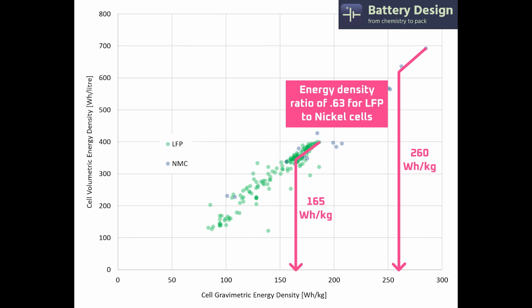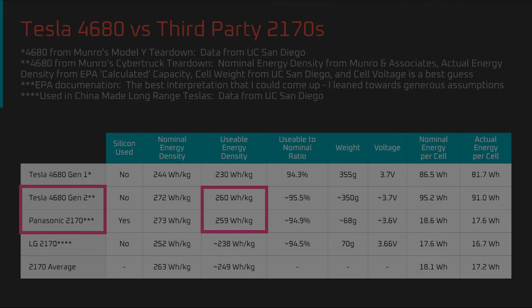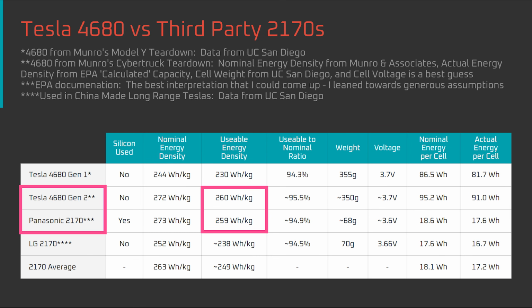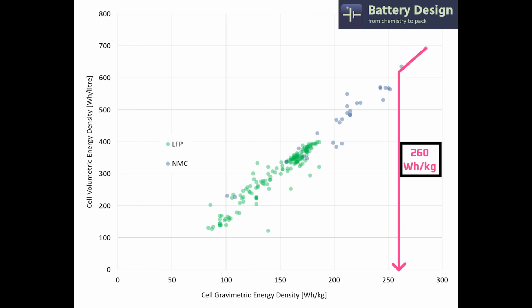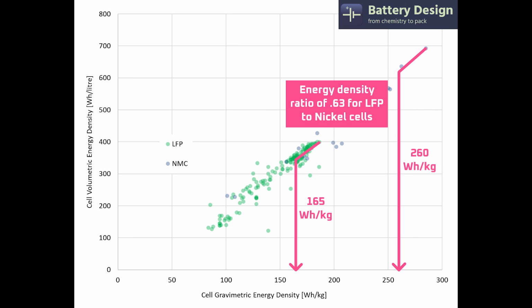Now that we've controlled for form factor using prismatic cells, let's apply that ratio to cylindrical cells. Cylindrical cells, such as the Generation 2 4680 and Panasonic 2170, have a usable energy density of 259 and 260 watt-hours per kilogram, which roughly aligns with the 260 watt-hour per kilogram usable energy density figure I estimated for a prismatic nickel-based cell. That means in order to estimate the range of an LFP vehicle, we just have to multiply the range of a vehicle that uses 4680 or 2170 cylindrical cells by 0.63.